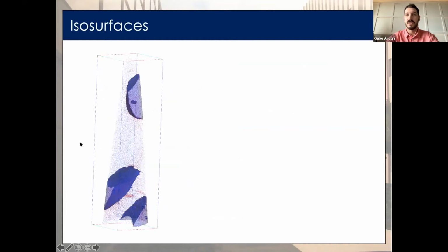Okay, so using this 3D grid, another way that we can quantify our data is by defining a surface at a given threshold. This is referred to as an isosurface. This analysis works by isolating blocks in our 3D grid having a specified range of composition or density for a given element, and then combining an array of adjacent blocks with the same defined range to create our isosurface. This isosurface then appears in our reconstruction as a highlighted region, which you can see here.